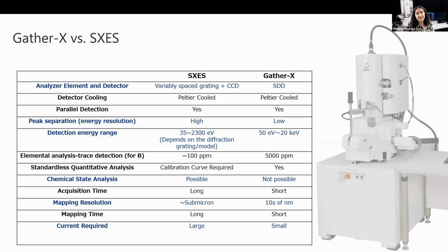I also want to mention that the SXES will not replace a standard EDS or WDS. Because of the energy range available, the entire range of characteristic energies cannot be reached with it. So it can only be used for certain elements and transitions. The SXES is used more for determining chemical state or trace element detection. And if you are interested in quantification, EDS or WDS is still best, since quantification with the SXES will require a calibration curve. So it's best to use the SXES to complement an EDS or WDS system.